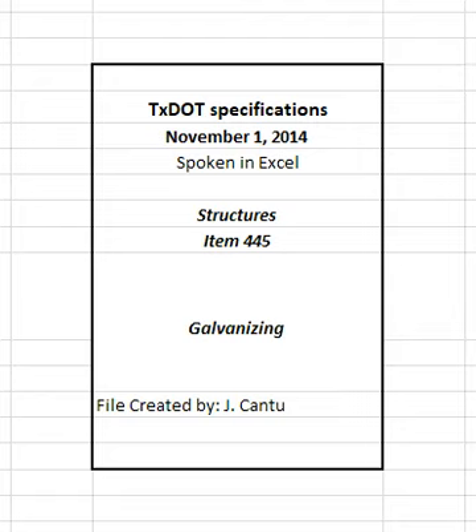3.4.4 Coating thickness. Galvanize to the thickness specified. Use Tex-708-I to determine coating thickness. 3.5 Repairs. Use zinc-based solders, sprayed zinc, or zinc-rich paints for repairs in accordance with this section. 3.5.1 Materials. 3.5.1.1 Zinc-based solders. Solders used in rod form or as powders. Zinc tin lead alloys with liquidus temperatures in the range of 446 degrees Fahrenheit to 500 degrees Fahrenheit or zinc cadmium alloys with liquidus temperatures in the range of 518 degrees Fahrenheit to 527 degrees Fahrenheit.